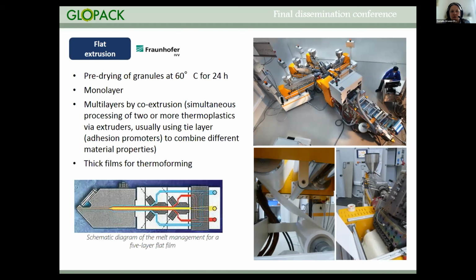Yes, flat film extrusion is one standard thermoplastic process to produce packaging materials. We always used a pre-drying step. This is important for all polyesters you want to extrude, also for fossil-based polyesters, because you have to avoid degradation at higher temperatures induced by humidity. With this flat film extrusion, you can produce monolayer films. And in case you have several extruders, you combine the different materials to a multilayer film structure with the different thermoplastic materials you use.